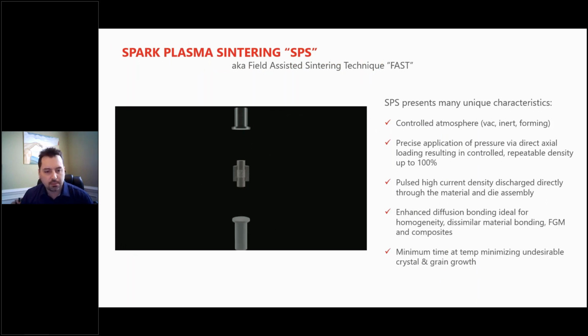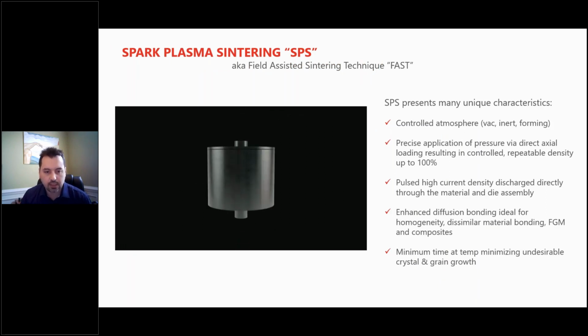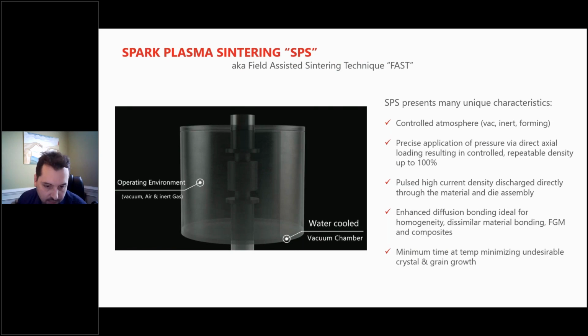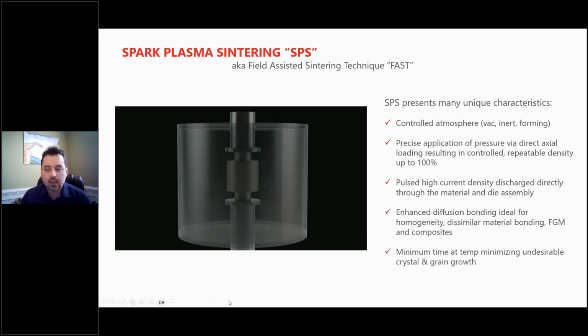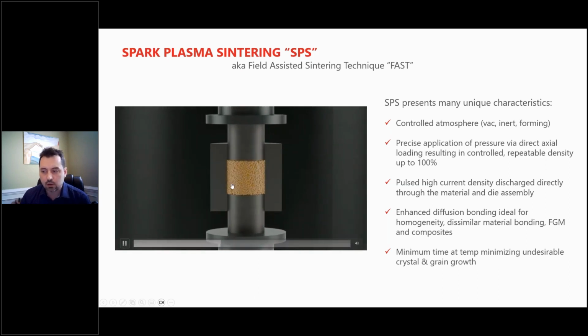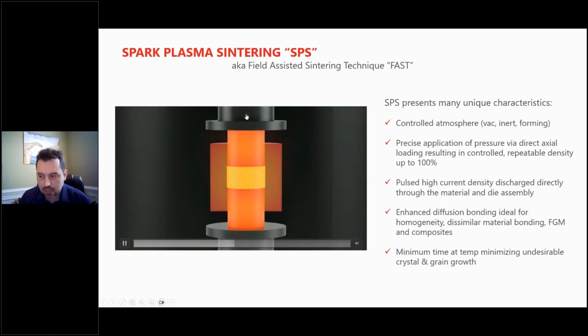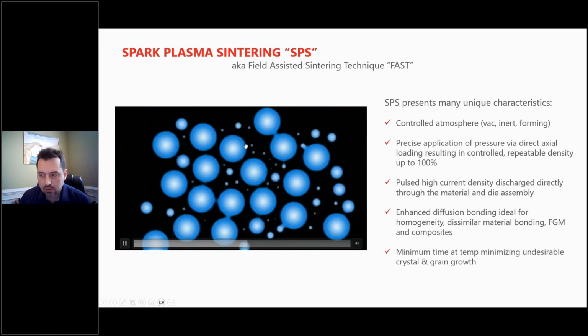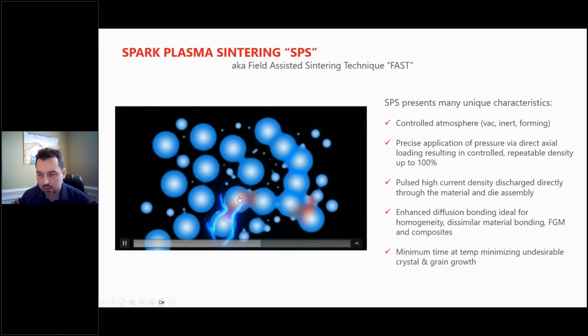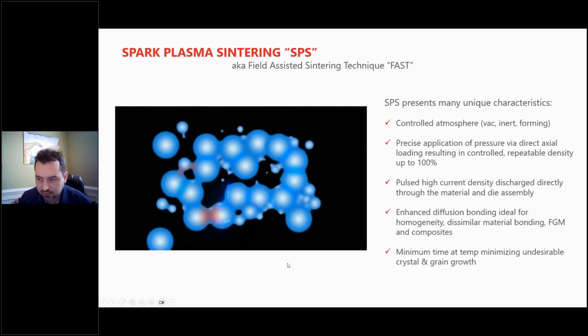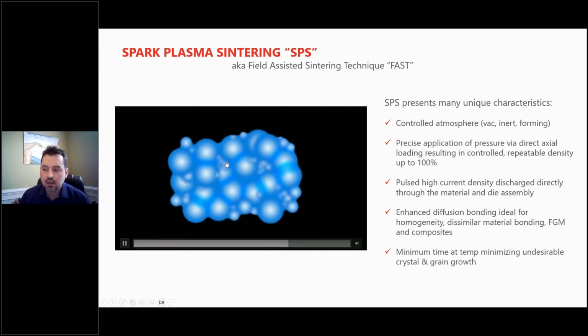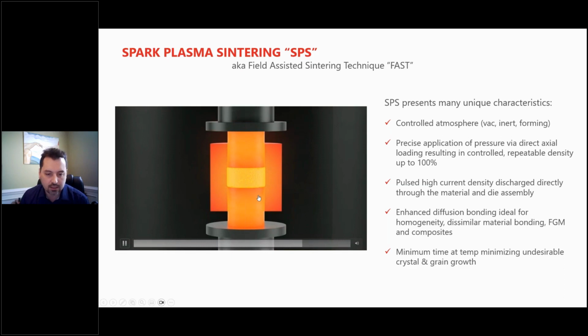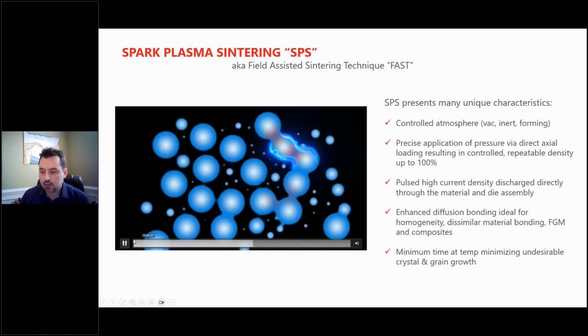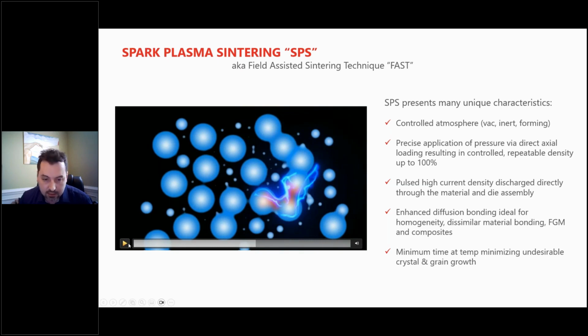So, as I mentioned, here's the basic setup. Typically we're going to be sintering in a vacuum atmosphere, but usually after an inert gas flush, nitrogen or argon. As I mentioned, you'll see here that we have our powdered material. In this case, it's in a cylindrical die. We're applying uniaxial force, and then we're going to pulse that current. So there's those sparks that don't actually exist in real life, but they help visualize the localized temperature increases on the particle boundaries. And so it's a very important differentiator compared to other sintering technologies.